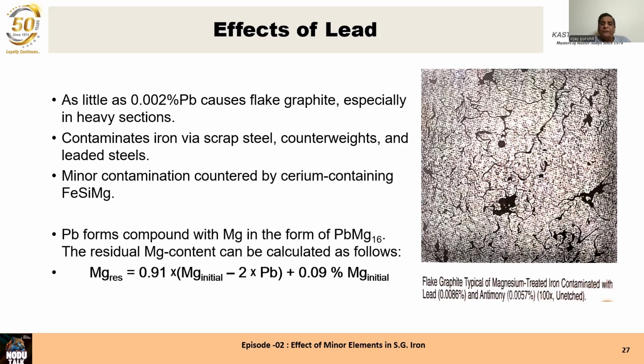Minor contamination of lead is countered or neutralized by the effect of ferrosilicon magnesium containing cerium. So, since you do not know exactly how much of these subversive elements are present, I recommend very strongly that you use rare earth containing ferrosilicon magnesium alloy to neutralize the effects of all these bad elements which are present to some extent or the other in your charge materials.